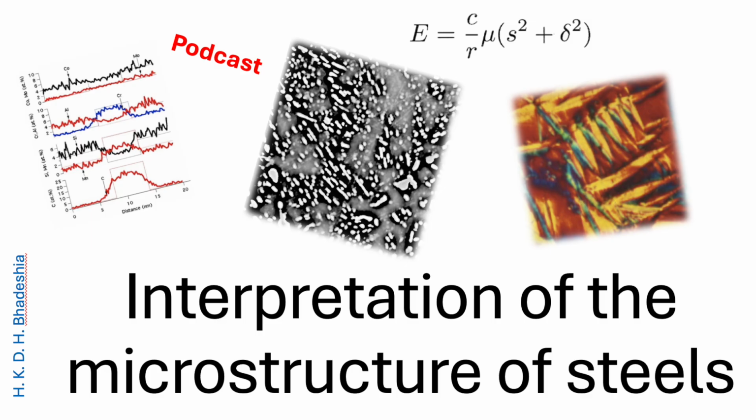Wait. So slicing that is just a 2D optical illusion? The whole colony is one continuous grain. Yes, the ferrite is a continuous phase, and the cementite is an interpenetrating continuous phase. This is vital, because while reducing the spacing between the lamellae makes the steel stronger, the colony size itself is the true crystallographic grain size. And that affects toughness. That dictates toughness, because a single cleavage crack can pass undeviated right across the entire colony. Low energy failure. That structural reality is key.